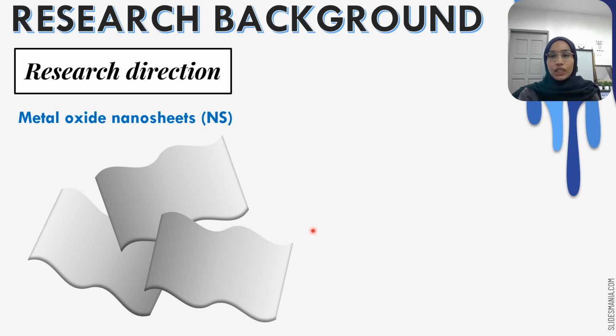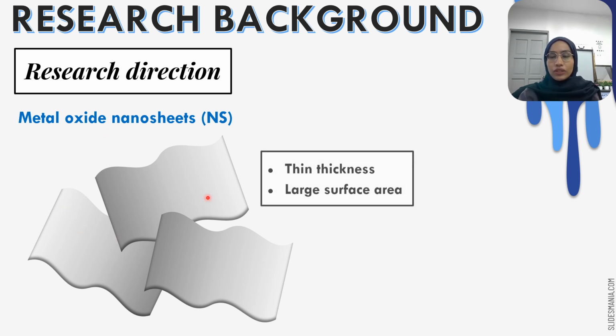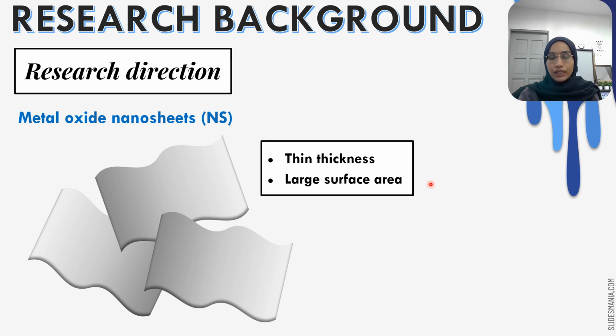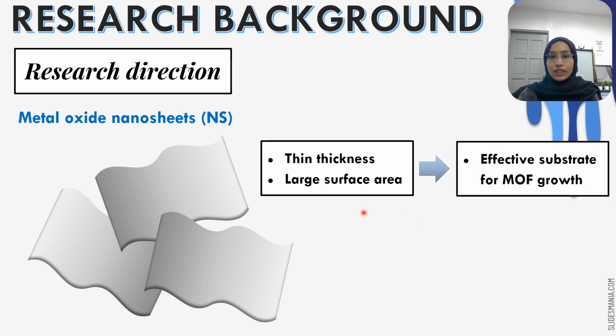For me, it is such a waste if we leave behind a really good material like MOF, even though it has low performance, especially in water absorptivity. There is still another way for us to improve its performance. So what I did in my research was I used another really good material, which is nanosheets. These nanosheets have thin thickness that can provide a very large surface area, so they can serve as an effective substrate for MOF growth.